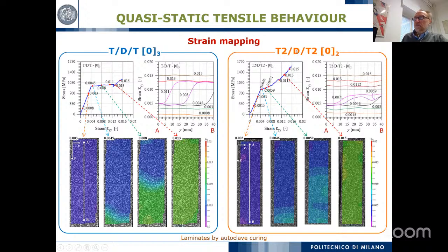If you change the sublaminate, the delamination starts, but it does not progress from one position through the entire specimen. It can appear at different positions, with different beginnings of delamination in different positions of the material. And this will give you the difference in the pseudoductility plateau, which is much larger than the other, because the delamination appears in different positions, and then the evolution is much faster than the first one.